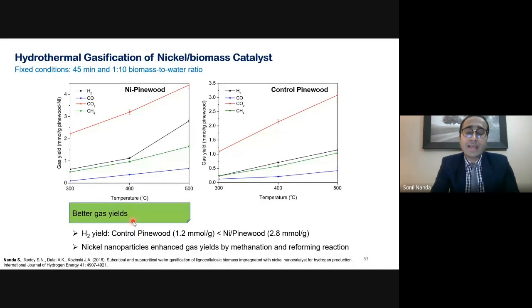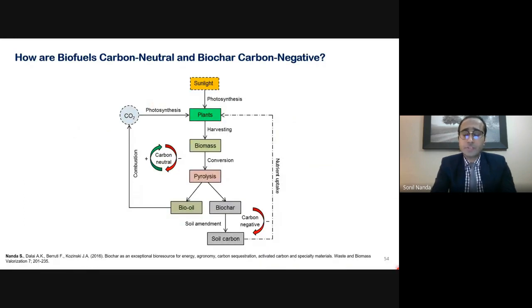And along with the hydrogen yields, the yield of all the gases, especially methane, also increased, because nickel has a catalytic effect in both methanation and hydrogenation reactions, as well as the water gas shift reaction. So it resulted in a decrease in the carbon monoxide yield, and then resulted in the production of more hydrogen and more methane when it was impregnated into the biomass itself. So this study determined that biomass can act as a reactant and also as a catalyst support that can adsorb the nickel metals or any catalyst nanoparticle metals within it, and can be effectively converted into different biochar and into the combustible gases. Now we are approaching the ending of this presentation with a few more slides remaining.